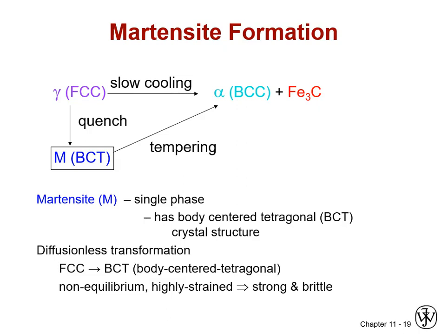Needless to say, the need to quench, which requires a tremendous amount of control, dimensional control, heat treatment, very expensive facilities, and the long times at temperature, both for austenizing and then the after-quench tempering, means these are expensive processes. So a quenched and tempered steel will almost always be far more expensive than an equilibrium microstructure. And of course, then we have to add the cost of machining it. In fact, since they are so hard, quite often they are at least rough machined to size before quench and tempering treatment.